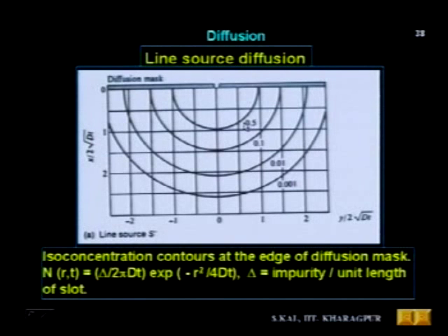N is the concentration divided by n surface, the surface concentration. That is this value, this C2. That means 0.5, if you see the contour, it looks like this. Similarly, the 0.1 contour is like this. The 0.01 contour is like this. 0.001 is again like this. This is a 2D plot. The x-axis is the vertical depth, so that is x by 2 root dt, and the lateral side is y by 2 root dt. So that means 2D iso concentration contours at the edge of the diffusion mask are like this.